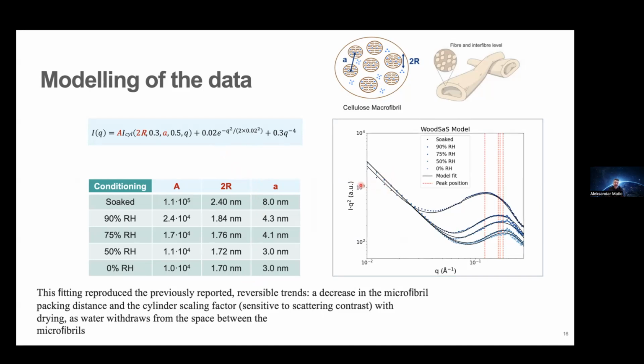And you can see here the results after fitting everything from a dry sample to a soaked sample, and then different degrees of humidity. And in this case, one could actually control the humidity by trapping the sample between two Kapton tape windows and having a saturated salt solution in the bottom of this to keep the right humidity. And you can see then that with increased humidity, you have a swelling of the fibril, but you also have an increase of the distance between fibrils. So this directly tells you something about the material.